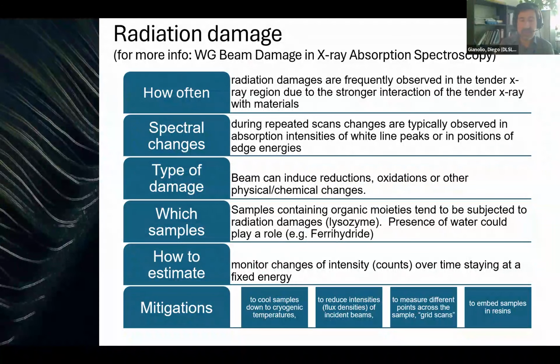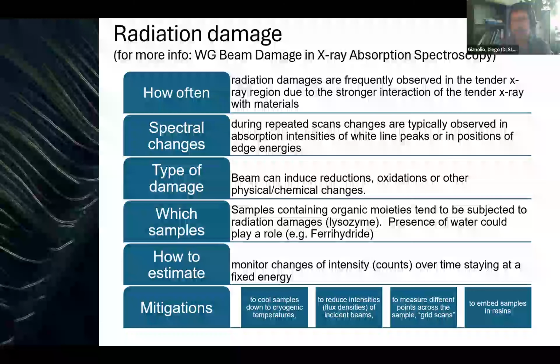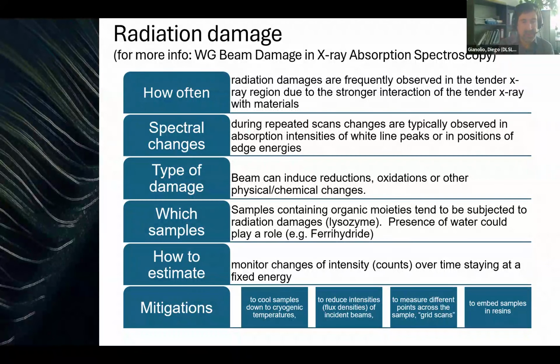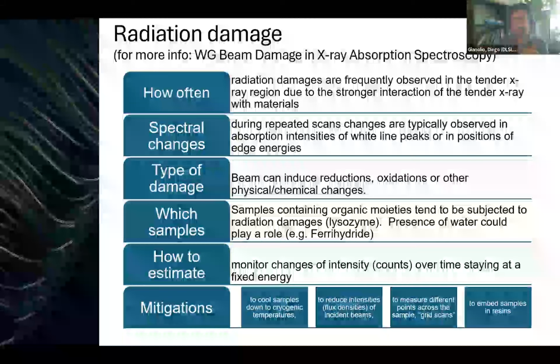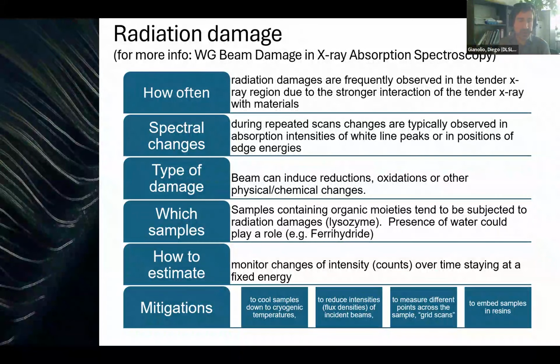And another thing that has been observed, since we sometimes do measurements in a controlled atmosphere, is that the presence of water could play a role. And this could be water inside the sample or water in the atmosphere that you're using to do the measurement. And so how can we estimate it? Well, normally you monitor the changes of the intensity of some peak or feature over time, possibly staying at a fixed energy to have a better energy resolution and not having to repeat the whole scan.